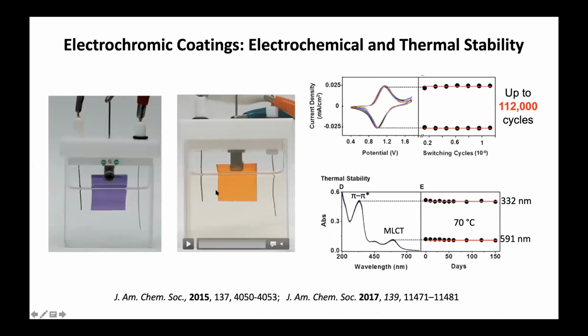So we take a certain film in an electrolyte solution. You see here very nicely when we oxidize the metal centers. On the left, it's iron, and on the right is ruthenium. You see very nicely the films become transparent. When we reduce the films, when we reduce the metal complexes, it returns to the ground state. And we can do that many times. The switching time can be much faster than will be possible to see by eye, but the time is also dependent on the diffusion of the electrolyte through the film.